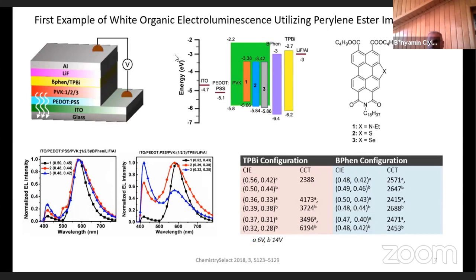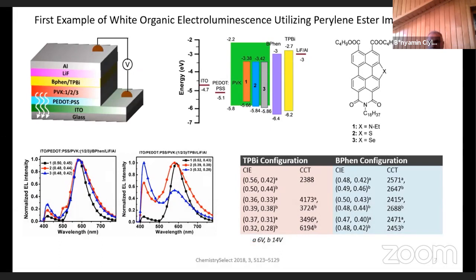In comparison, TPBI results in a lower electron injection barrier at the TPBi-PVK interface, which facilitates more electron injection into the emissive layer, thus resulting in increased recombination. In this study with TPBI, good enough white light was obtained by balancing blue and orange-red emission. However, the green region of the visible spectrum is missing. This results in low CRI, and the electron transport layer is coated by vacuum thermal evaporation. These are the drawbacks of this study.